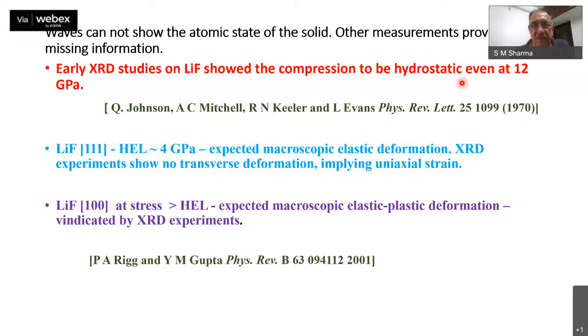And a lot of theoretical work has gone into studies of this. It required invocation of a variety of kinds of defects which contribute to the plastic deformation. And incidentally, the plastic deformation is the key to the whole rationalization, that the plastic deformation takes away the deviatoric stresses and therefore relaxes the local strain from uniaxial to hydrostatic. Having said this, the geometric conditions of the material require that the macroscopic strain is still uniaxial. Microscopically, it has become hydrostatic. Macroscopically, it is still uniaxial.